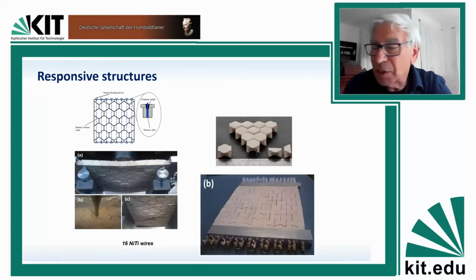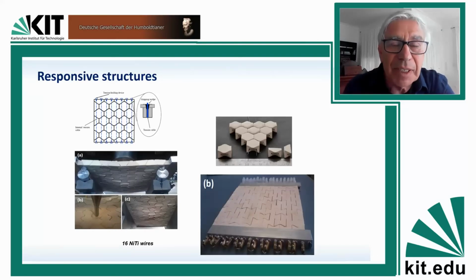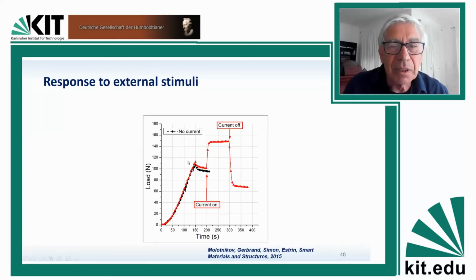You can also give the structure responsiveness to external stimuli. In this case, we just passed shape memory wires through the material, loaded this material, stopped the loading device. There was a bit of load or stress relaxation, and then we passed an electric current through those shape memory wires. That is, we heated the wires instantaneously, or almost instantaneously, and there was a rise in the load here, which came as a response to that. And if you switch the current off, you get back to the continuation of this load relaxation line.